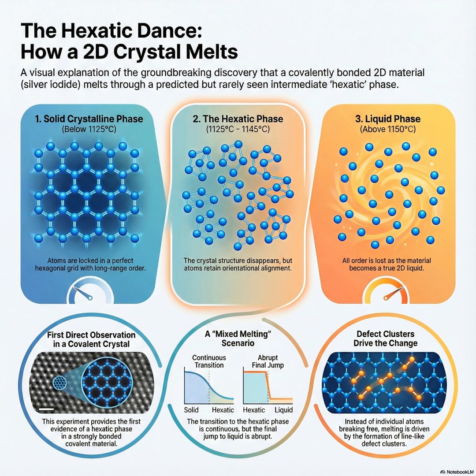But that's not what they saw in the silver iodide. No. They saw a very high density of lower energy defects that rapidly clustered together. Instead of being isolated points of weakness, these defects formed massive, line-like clusters. So they formed borders. They formed sharp physical borders, what are called grain boundaries, between the highly ordered hexatic phase and the fully disordered liquid phase. And those grain boundaries are what created the sharp division that drove the abrupt first-order transition.